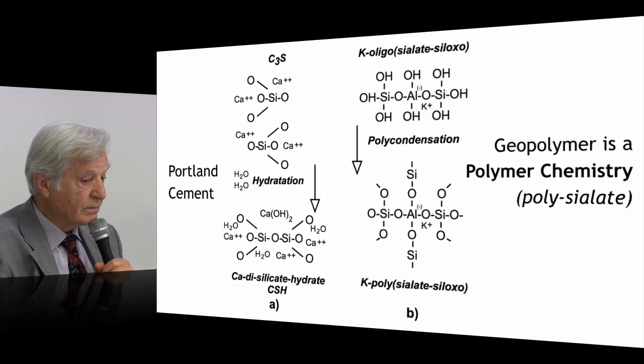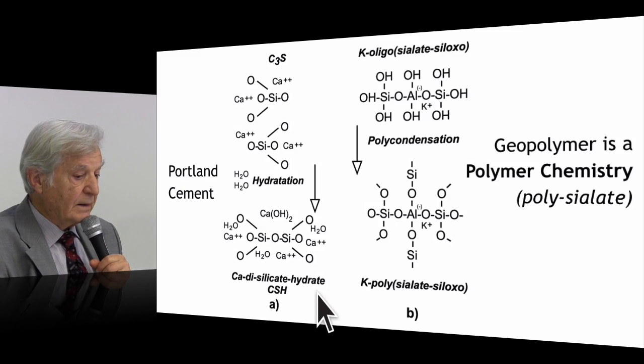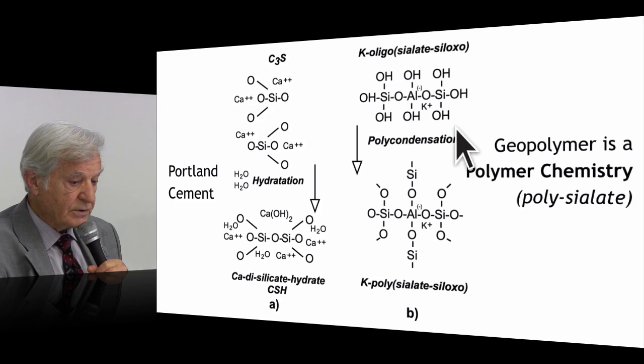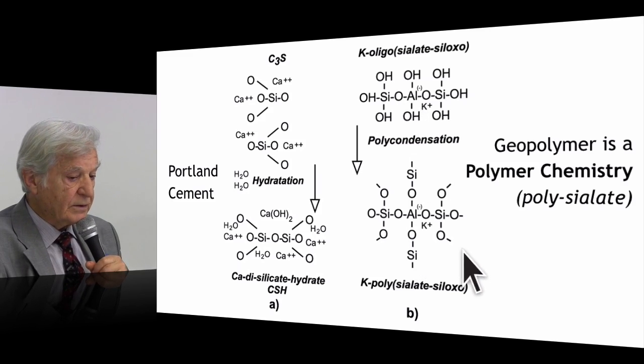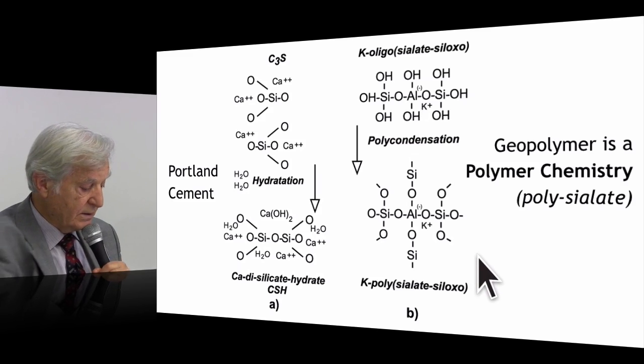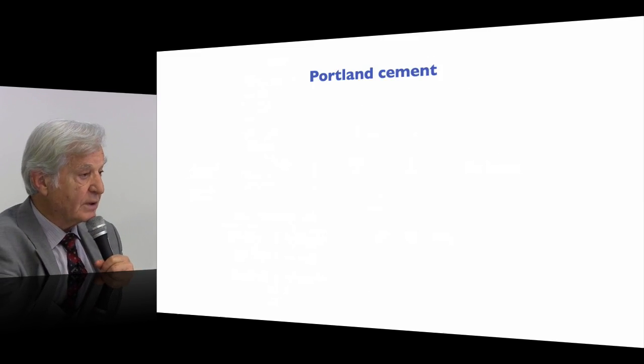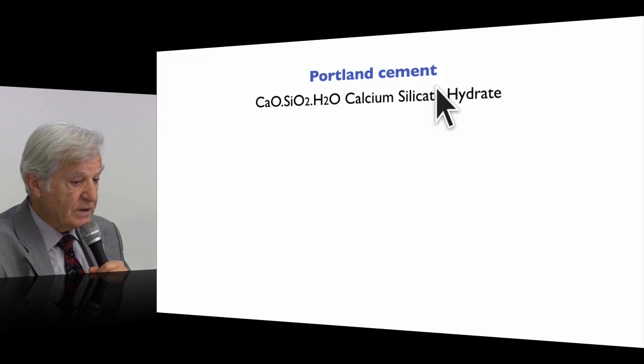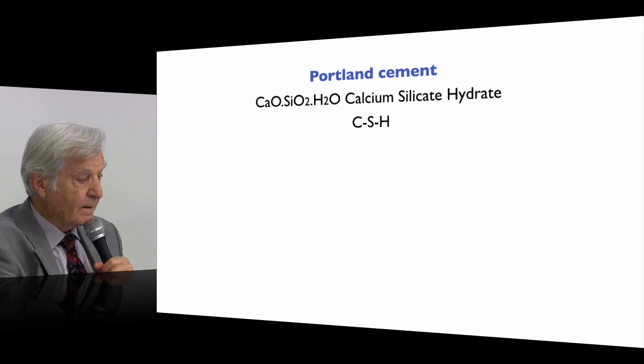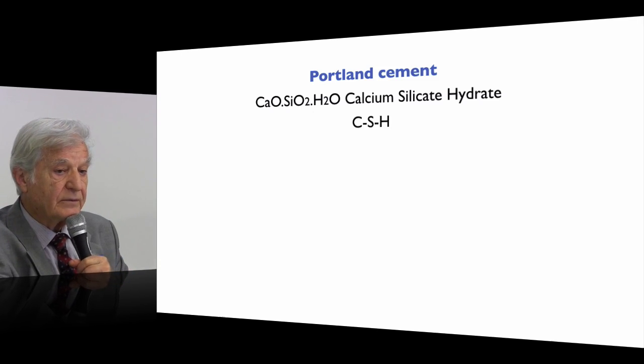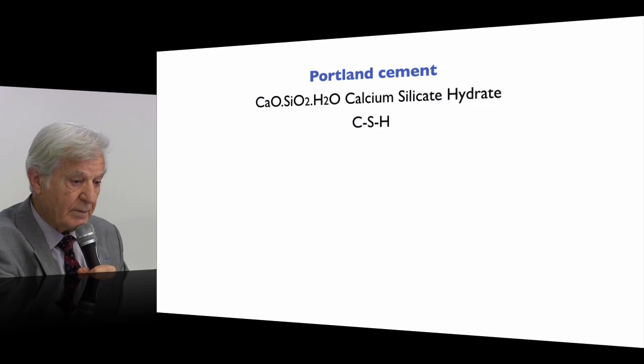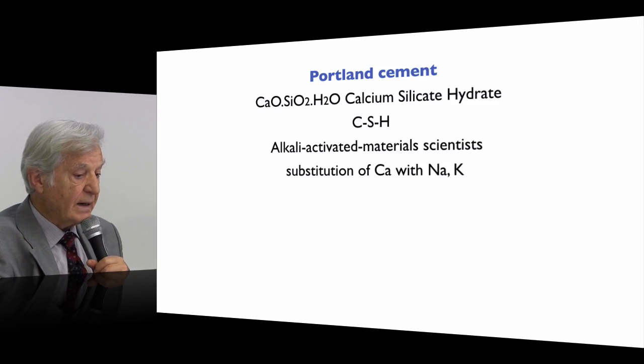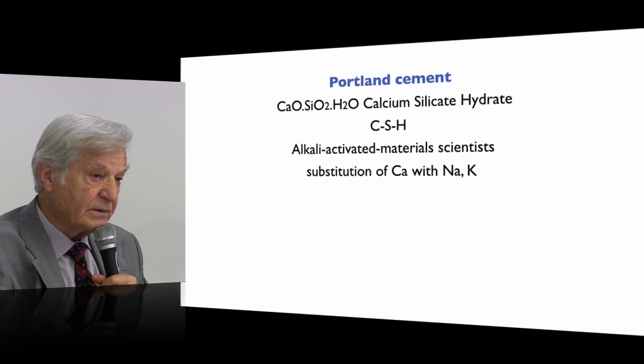This is geopolymer chemistry. It has nothing to do with it. You have the polymerization, the polycondensation of molecules that build a network. And this is a polymer. But cement scientists, who are accustomed to Portland cement terminology with their calcium silicate hydrate, CaO, SiO2, H2O, that is CSH, when tackling so-called alkali activation or geopolymers, in their mind substitute the calcium with the sodium and the potassium, and are starting to make a big chemical mistake.